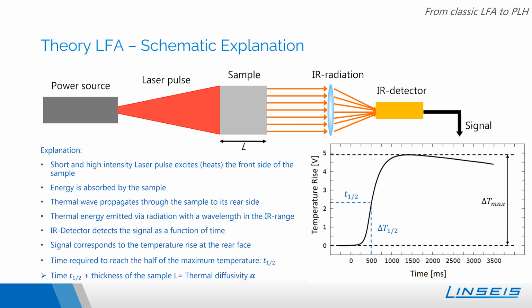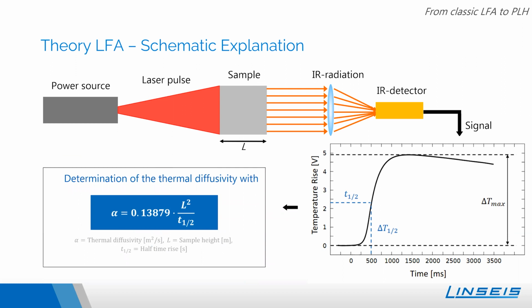And as you see, a signal like this can be seen in the detector, and out of this signal you can calculate the time which is required to reach half of the maximum temperature, the half-time rise. And out of this time and the thickness of the sample, you can calculate the thermal diffusivity with this basic formula. So the thermal diffusivity is 0.13879 times the square of the thickness of the sample divided by the half-time rise. To optimize this process of finding the half-time rise, Linseis' software package offers several evaluation methods.